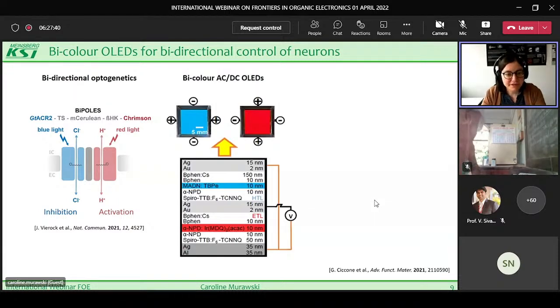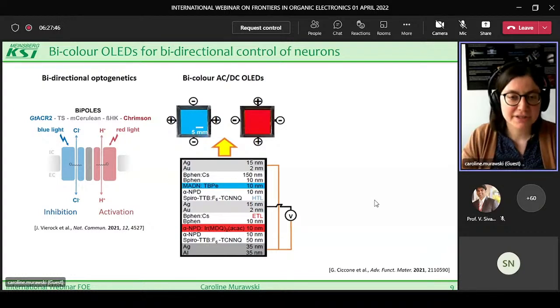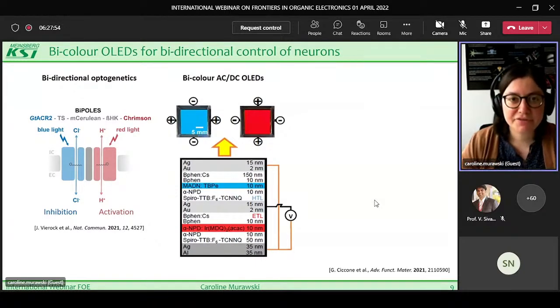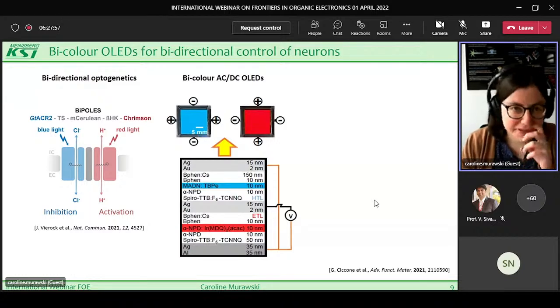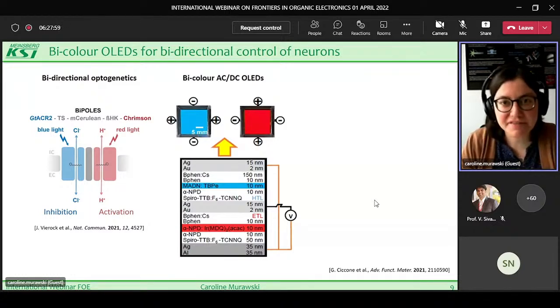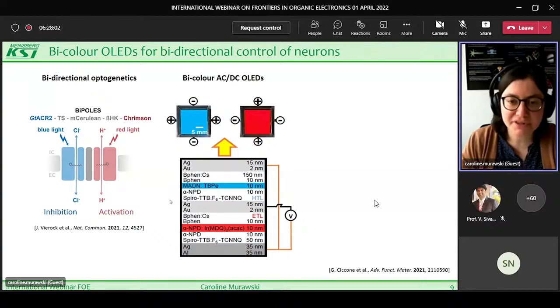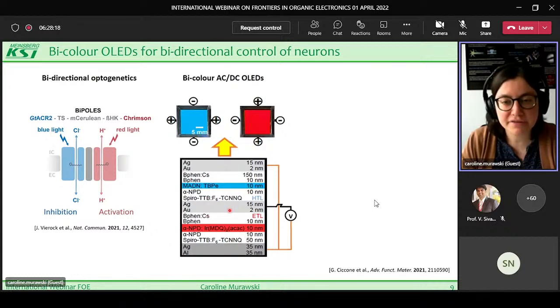And we thought OLEDs are actually the perfect light source to do this, because we can stack them on top of each other in order to provide emission from exactly the same spot, but with 2 different colors. For this reason, we've developed these bicolor AC/DC OLEDs. The actual principle is already some years older, and was developed at TU Dresden. The idea is that we have a phosphorescent red OLED on the bottom and a fluorescent blue OLED on top. So that's a top emitting device in total.